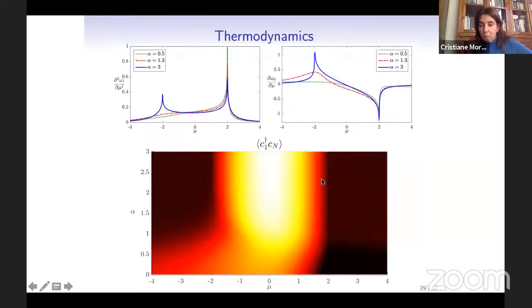So we can look again in different cuts how these things are behaving. And we see for 3, we have very sharp phase transitions at -2 and 2. But for 1.3, this became smooth, and 0.5, too. Here you see that for the boundary, it's still some bump, but then for the 0.5, it becomes smooth.